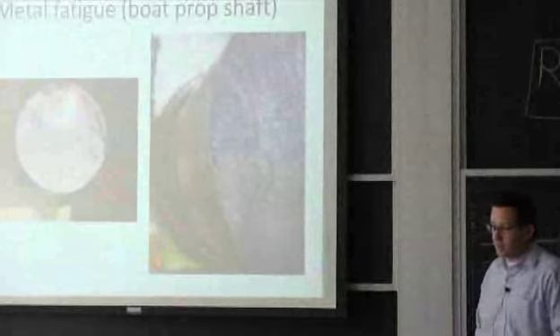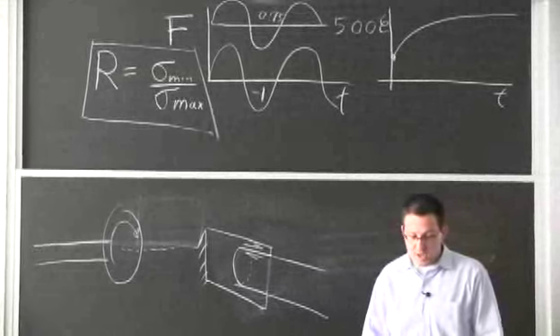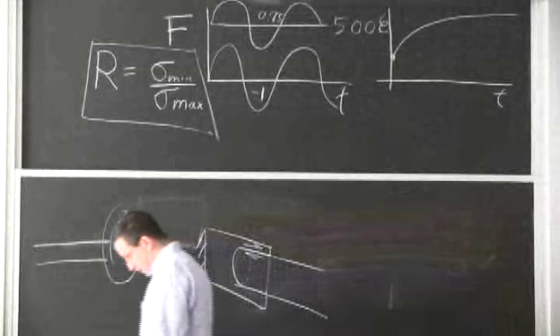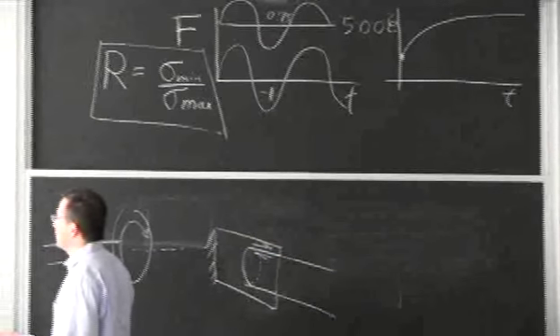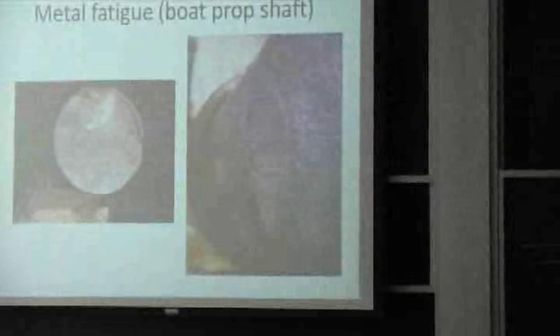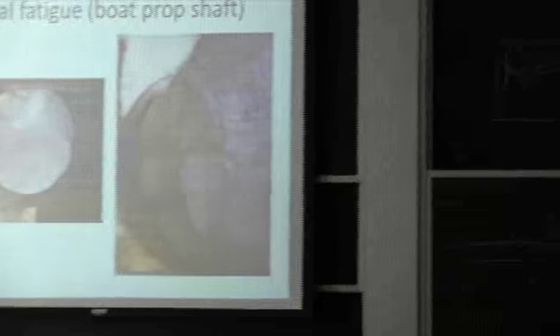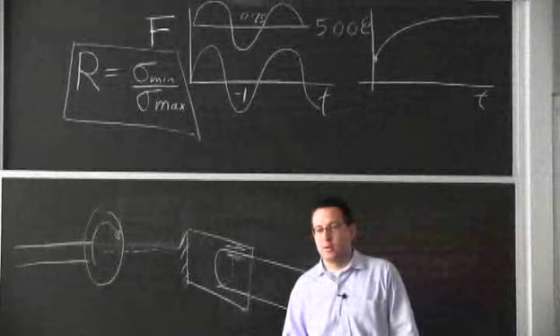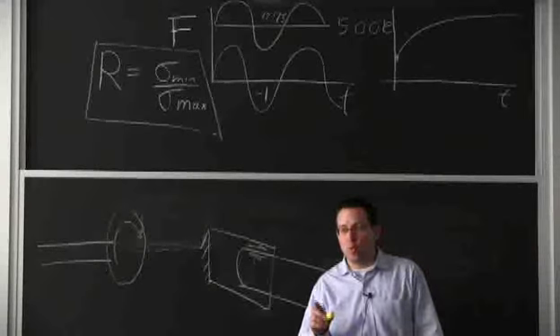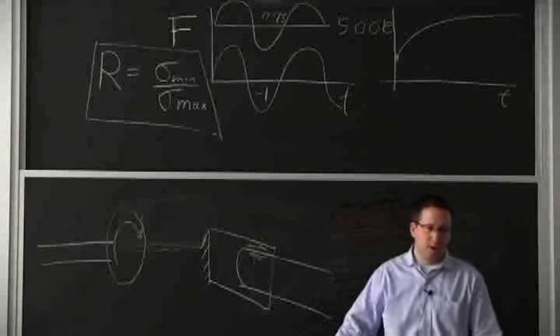And we have some material properties that we use to figure out approximately what that load was based on the crack size. And that's also something we'll cover in the class, but I wanted to bring it up right here. There's a blow-up image on the right-hand side. That's your initial flaw size. So it is visible. If I could bring that shaft in, you can see it if you're careful, but it's small. On a 6-inch shaft, it may be 0.5 millimeter. But even at 0.5 millimeter, you can tell that it started from one place and went all around.